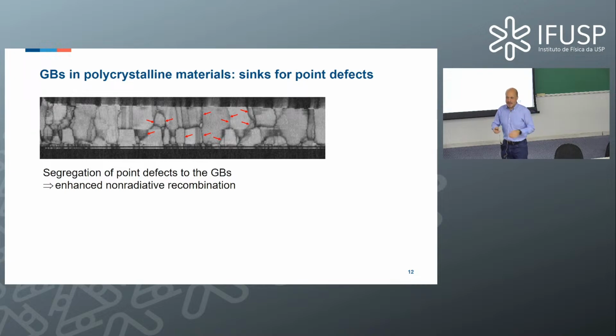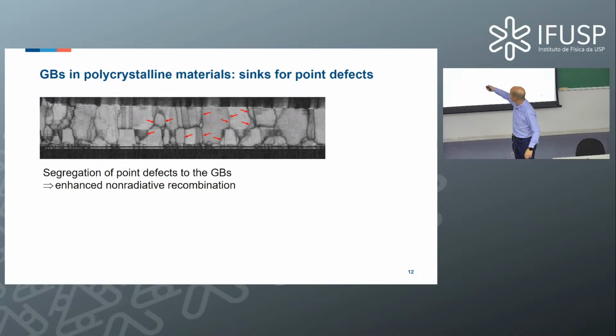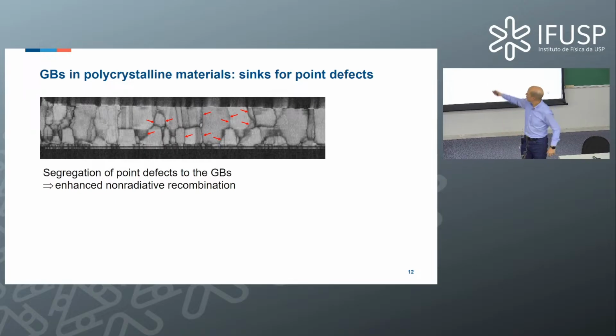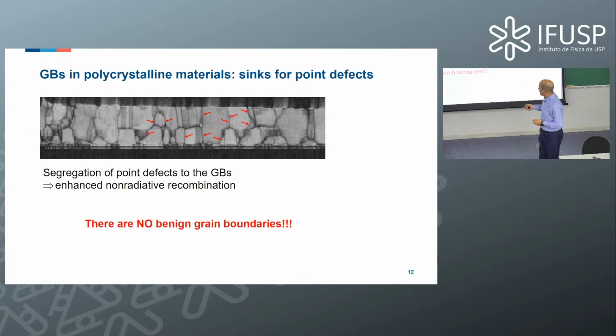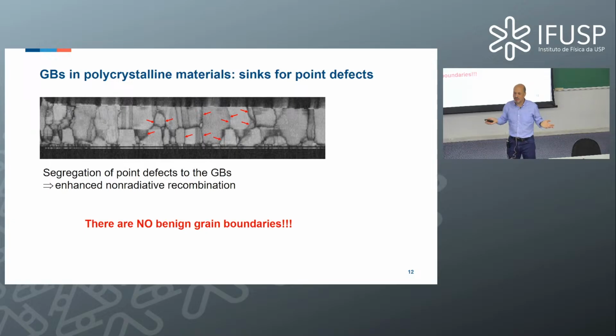yeah? So anything, point defects, impurities, anything that disturbs the lattice is pushed to the edges, which is why they segregate at grain boundaries or at surfaces. Yeah? And so what we find here is a higher density of defects, and correspondingly, we have enhanced non-radiative recombination of the charge carriers via the defects. So this is why you will never find benign grain boundaries, because in a way they're always detrimental, okay?